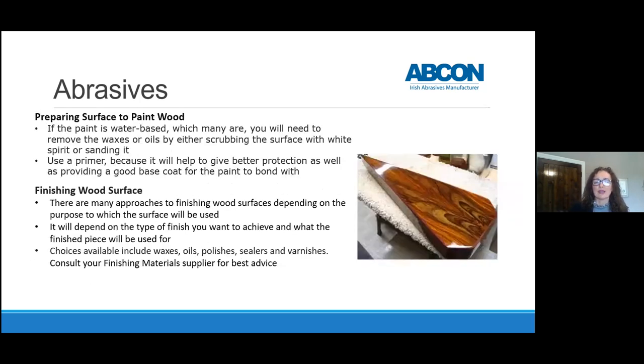When you're preparing a surface to paint wood, if the paint is water-based, which many are, you'll need to remove waxes or oils by scrubbing the surface with white spirit or sanding it. Always good to use a primer because it'll help to give better protection as well as providing a good base coat for the paint to bond with.